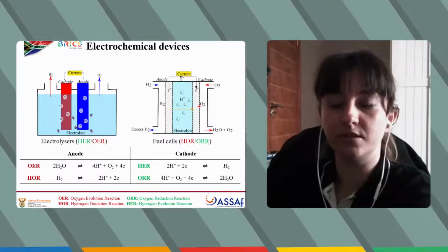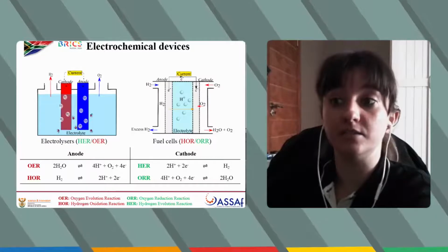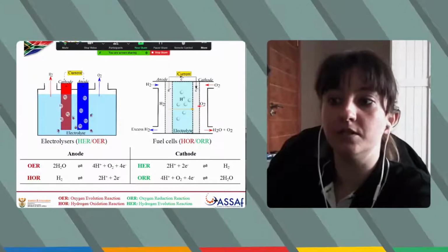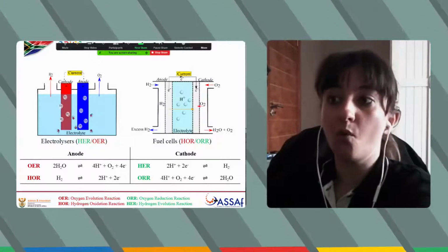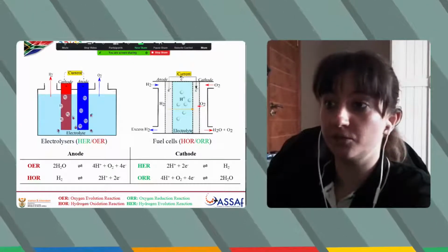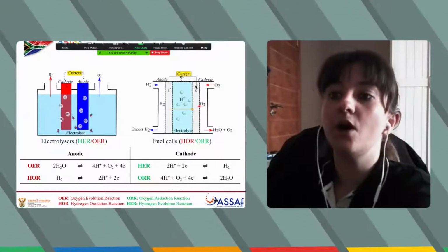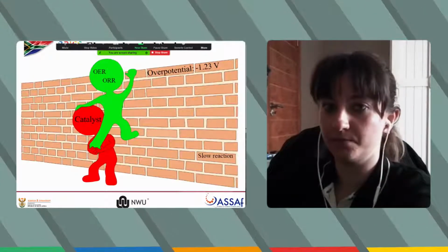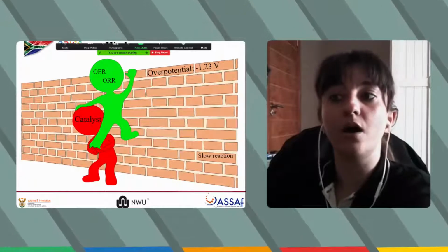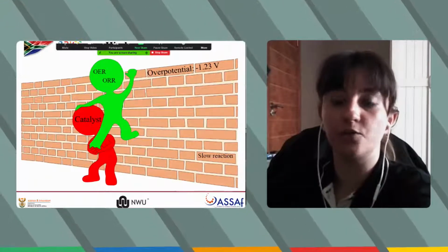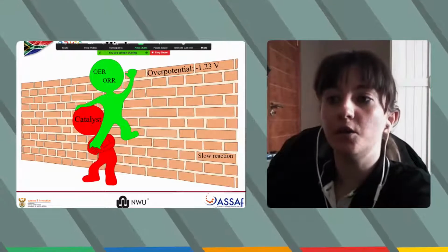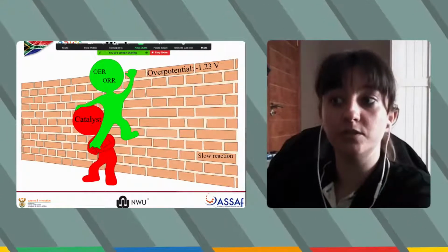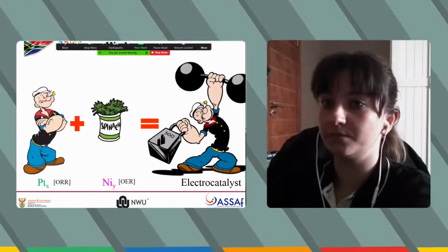electrolyzers and fuel cells. The electrochemical reactions that take place on the anode are the oxygen evolution reaction and the hydrogen oxidation reaction, while the oxygen reduction reaction and the hydrogen evolution reaction take place on the cathode. However, the oxygen evolution reaction and the oxygen reduction reaction are hindered. These two reactions require high overpotentials, and due to this, the reaction kinetics are slow. In order to lower the overpotential and to increase the reaction rate, a catalyst is required.